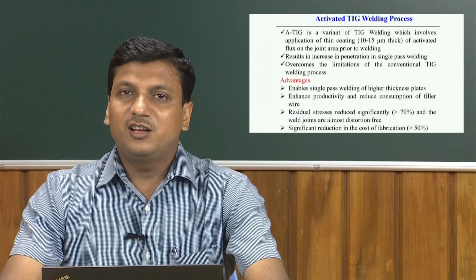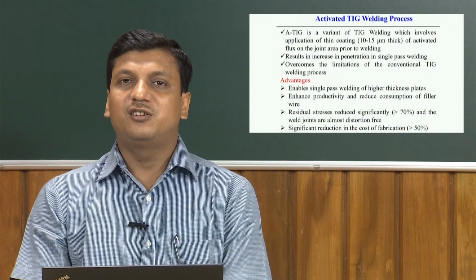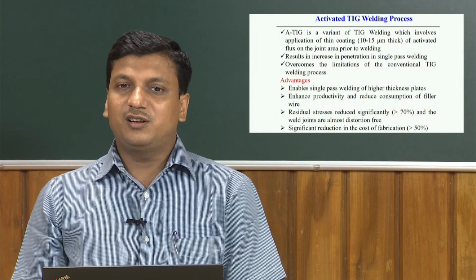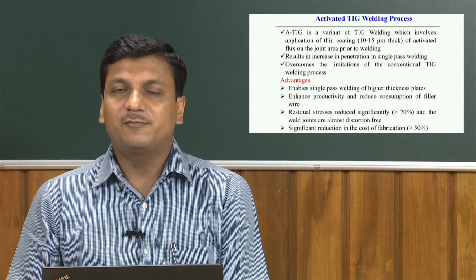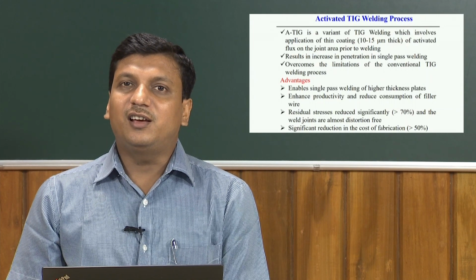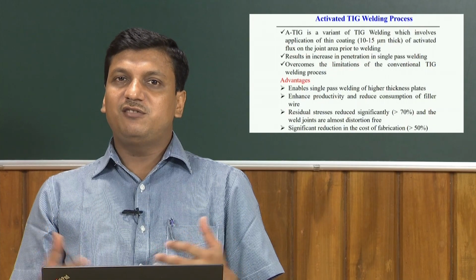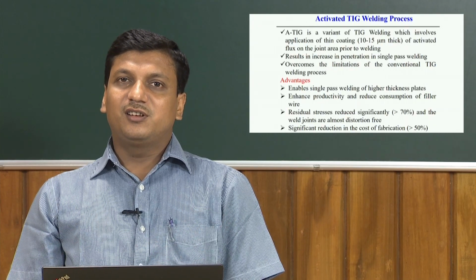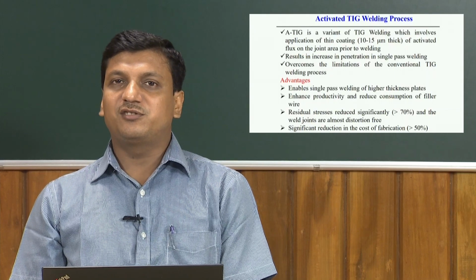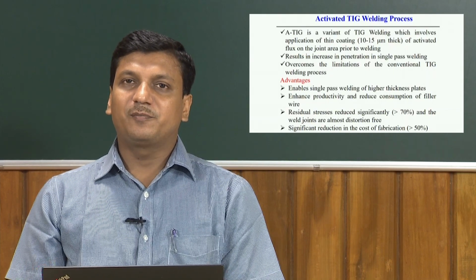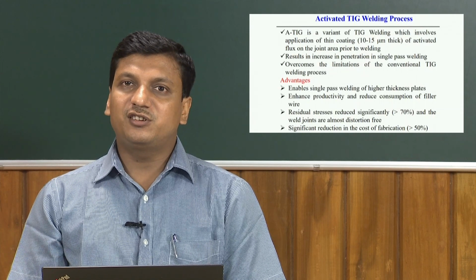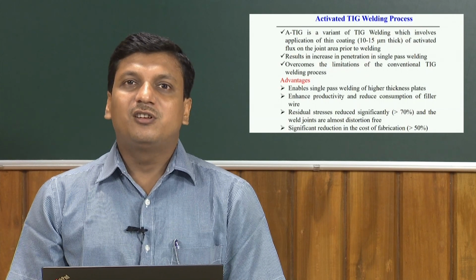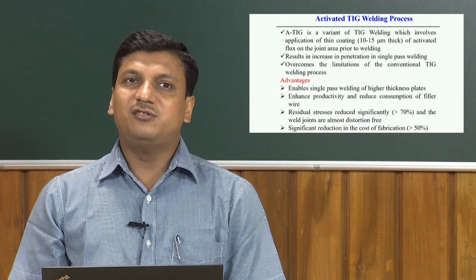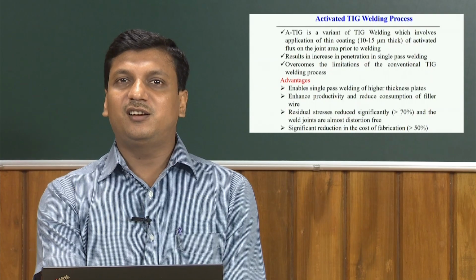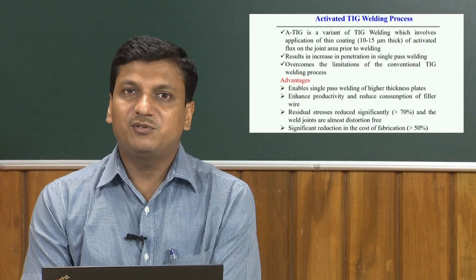Distortion can be avoided using this activated TIG welding process, and of course, the significant reduction in the cost of fabrication, more than 50% in general, because compared to the laser welding process, the normal TIG welding process is low cost. Laser welding can achieve a high depth of penetration because of the high concentrated heat, but even TIG welding can achieve a high depth of penetration, only we need to modify this by including the effect of the surface active elements.